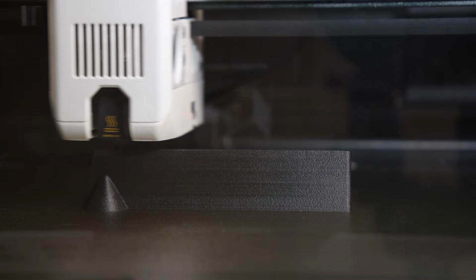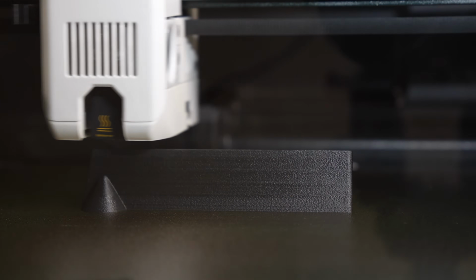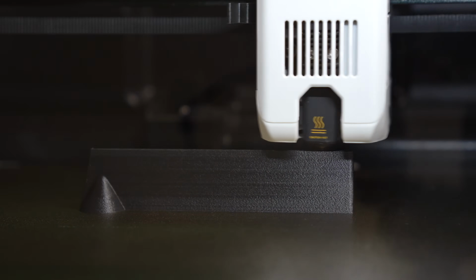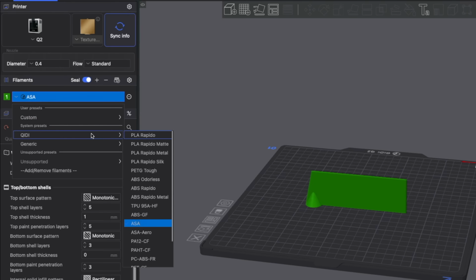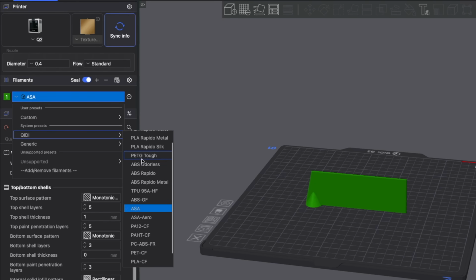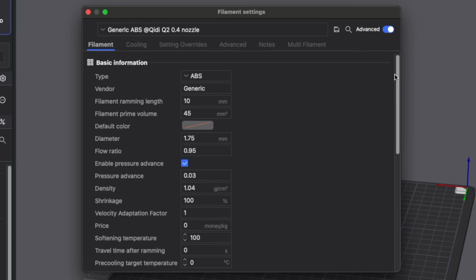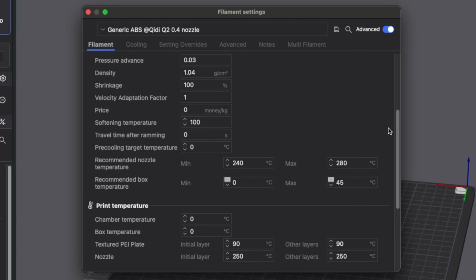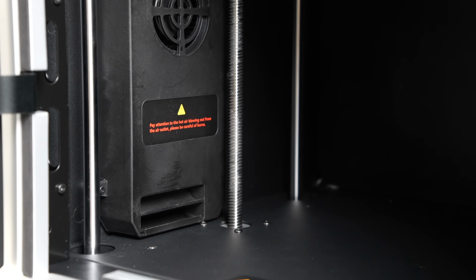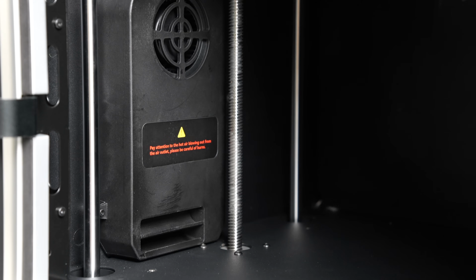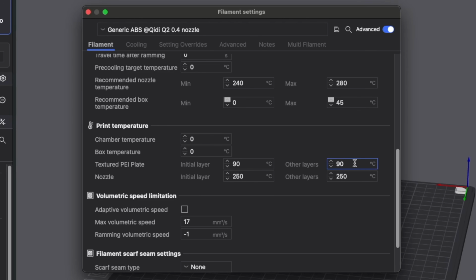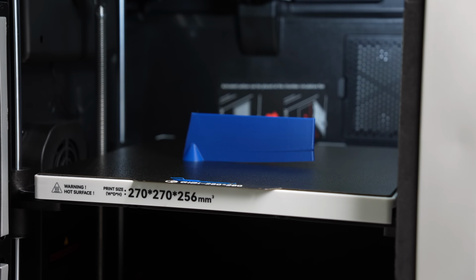PLA, PETG, and carbon fiber nylon printed on both sides of the build plate without any issues, so there was absolutely nothing to compare. For all materials that had existing profiles in Qidi Studio, I kept all of these settings stock. For ABS specifically, the only profile available was under generic, and while the Q2 does have an active heated chamber, the profile had it set to 0, so I did not run the heated chamber while printing out ABS. For the part without adhesive, it began warping at about 25%, but it still held on to the build plate and was able to complete.